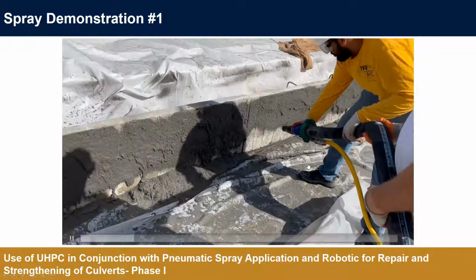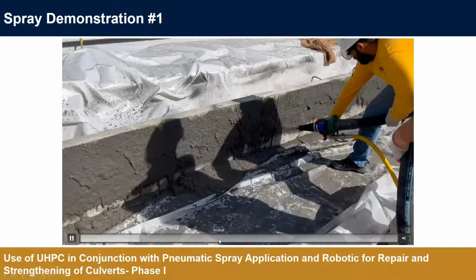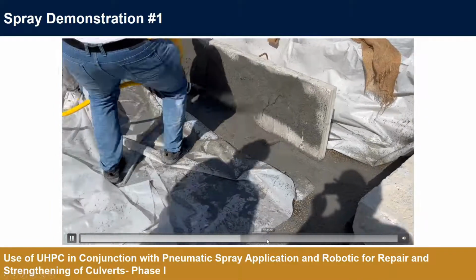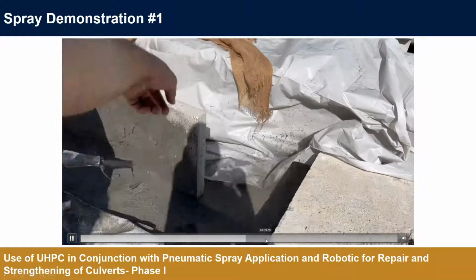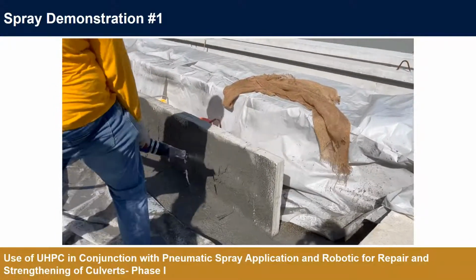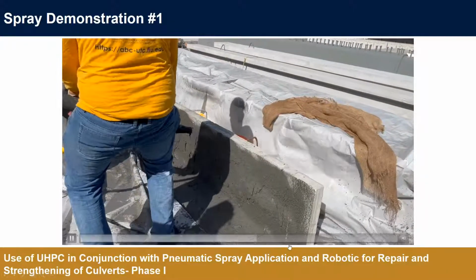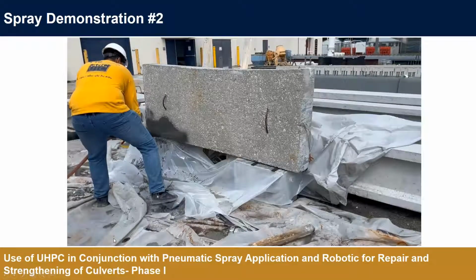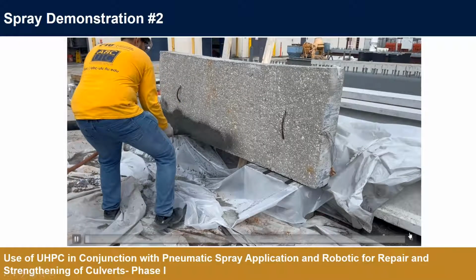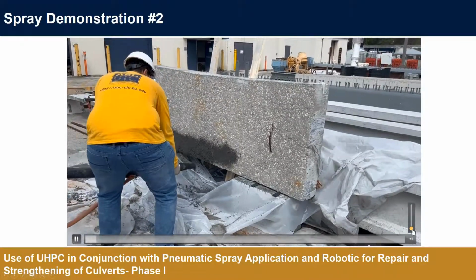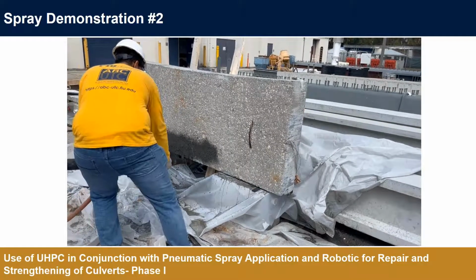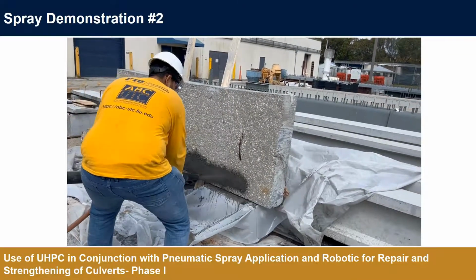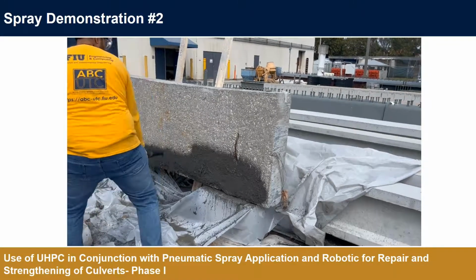And at the end, if I just move the video faster, you can see that the specimen was really on the ground in the beginning, and it was tough to reach the bottom, but as you can see here, we were able to shoot the concrete, or the UHPC, with fiber. We did another trial with this specimen lifted 2 feet above the ground, and we were able to shoot the material over this concrete substrate very nicely with fibers.